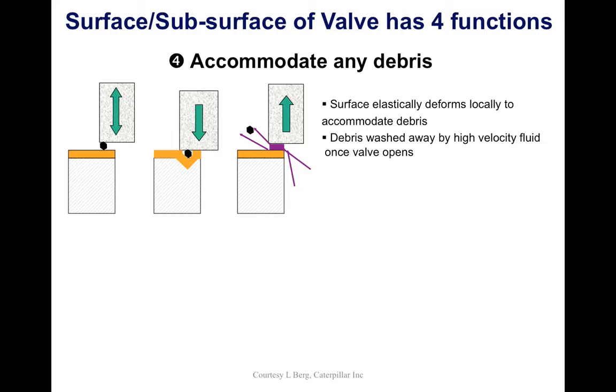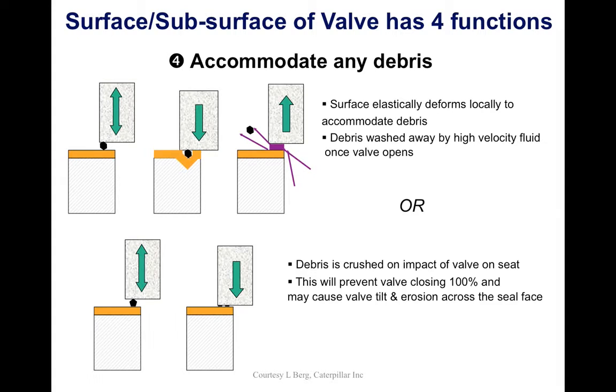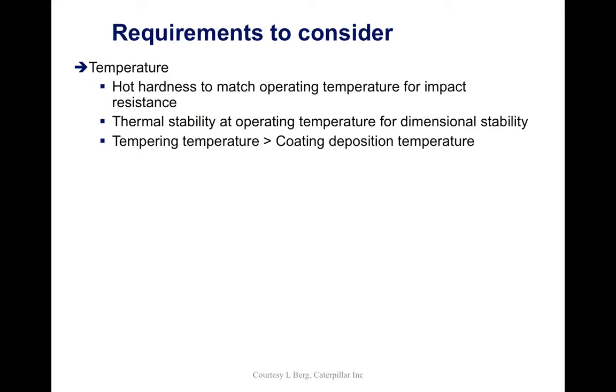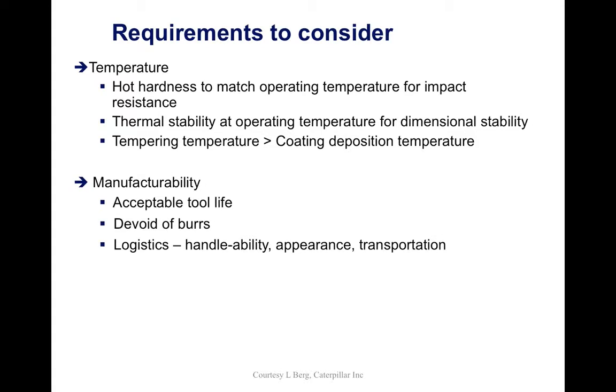And that means that the surface should elastically deform locally to accommodate the debris, and then the debris can be washed away, or the debris can be crushed, so you need a hard coating to crush the debris and then wash it away. So there are other requirements to consider when you make the selection. The temperature requirement, the hot hardness has to match the operating temperature for the impact resistance. There's got to be thermal stability at the operating temperature for dimensional stability, and the tempering temperature has got to be higher than the coating deposition temperature.